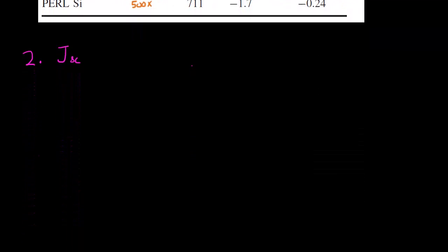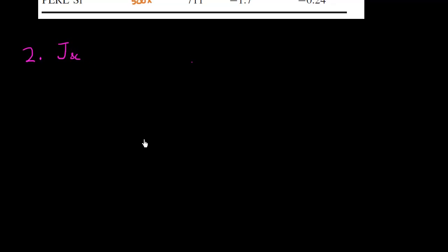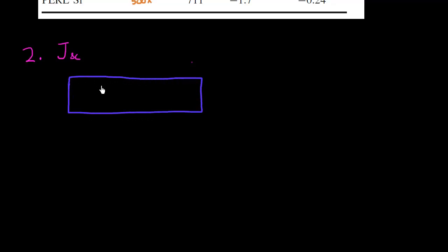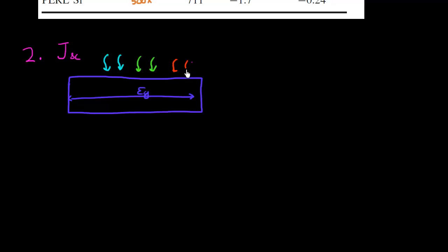The other thing I'm interested in is how the short circuit current JSC behaves as a function of temperature. For a single junction cell with one material system, increasing temperature decreases the band gap. As a result, the cell can absorb more of the solar spectrum — for example, a cell that was only marginally absorbing green light can now absorb more of it. As a result, JSC typically increases as you increase temperature.